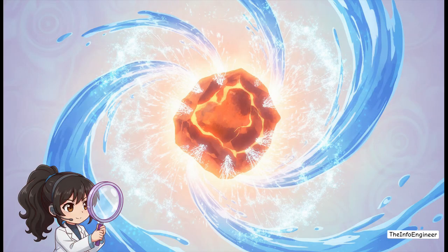So, ignition. When water hits this powder, an exothermic reaction immediately kicks off. It literally starts generating its own heat. The C3A tries to react super fast, but remember our gypsum timekeeper? It steps right in, forming a microscopic, protective layer called ettringite around the cement grains to throttle that reaction speed. Again, this is what gives the crew the time they need to pour foundation.